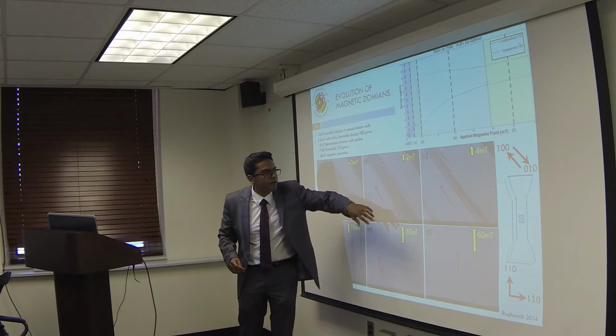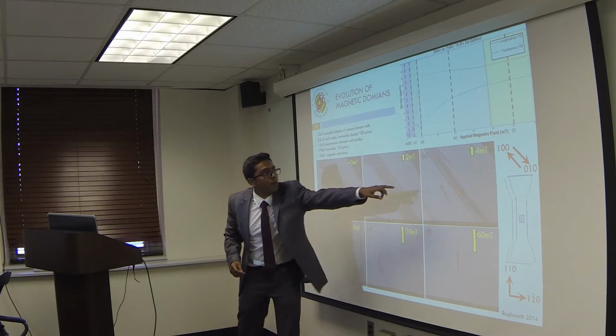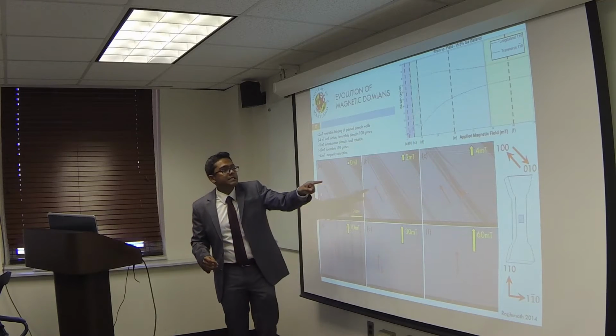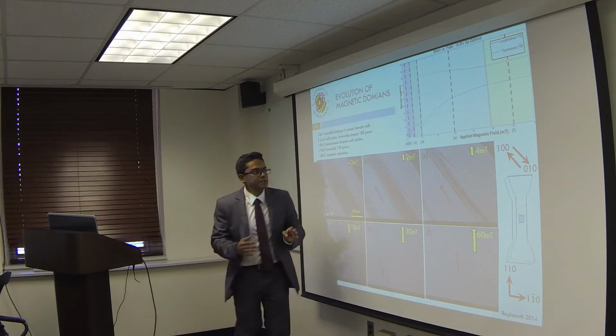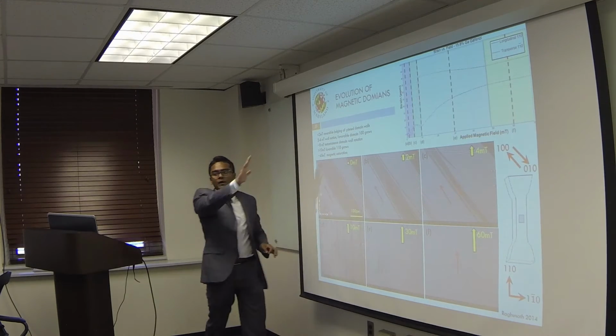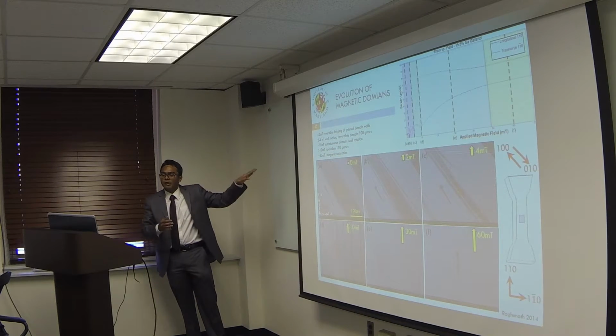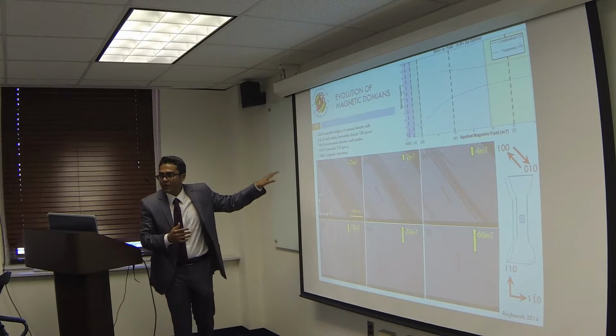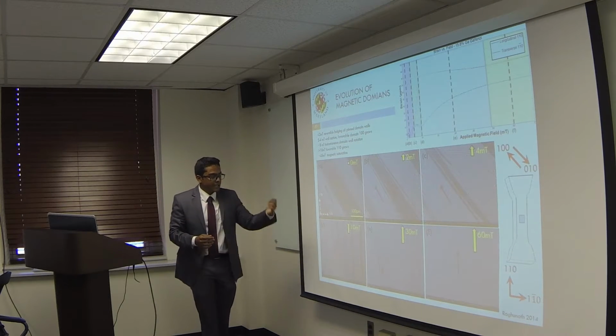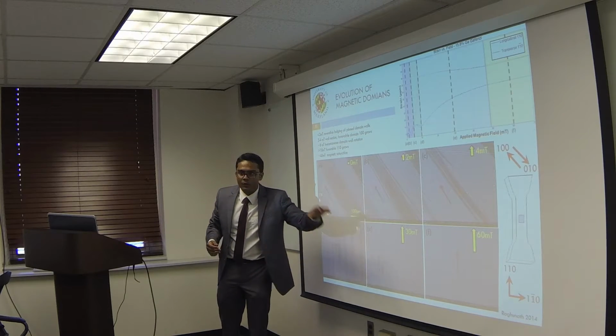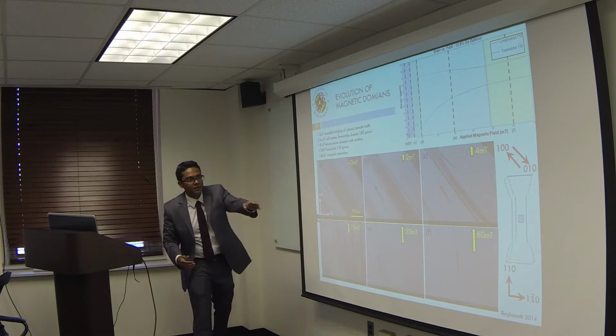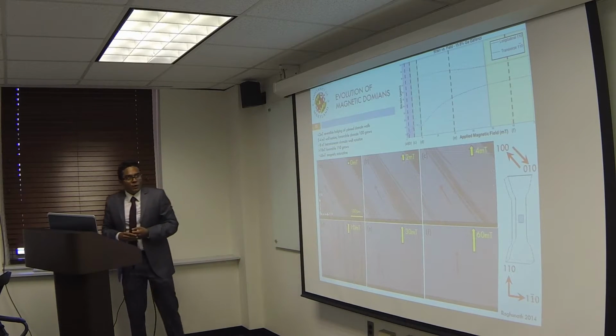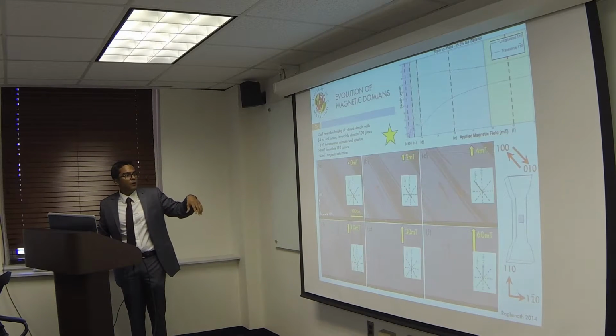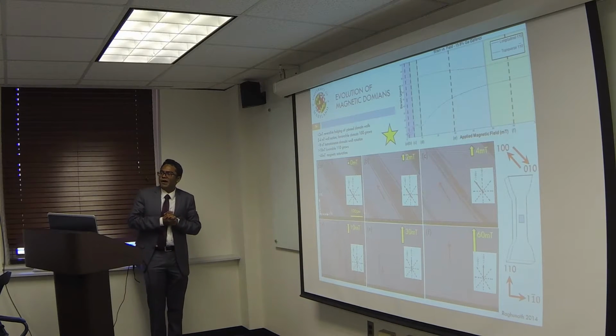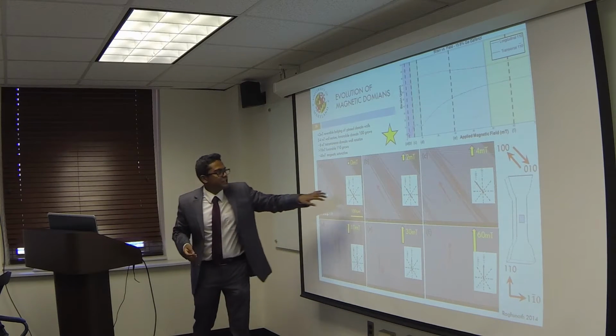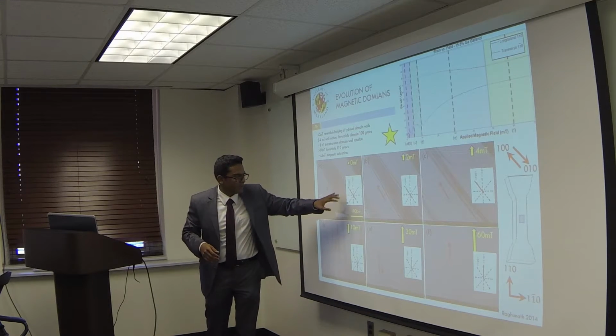So you can see this growing bigger and bigger until we reach a point which is C, which is right there. And past C, for an applied magnetic field, this seems to rotate to orient itself along the applied magnetic field. So from being oriented along the 100 direction, we're now oriented along the 110 direction. And as I keep applying more and more field, the unfavorable domain diminishes, and we attain magnetic saturation at F. So based on what we saw here, we had to modify the proposed model. This is the modification that we had to come up with.